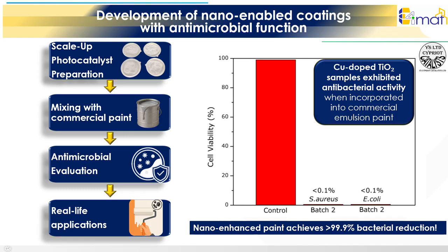The results show a dramatic difference compared to the control paint. While the untreated coating allows full bacterial survival, the nano-enhanced paint achieves more than 99.9% reduction for both S. aureus and E. coli. These results demonstrate that incorporating the copper-doped titanium dioxide particles provides strong antibacterial properties, highlighting the potential of such coatings for real-life applications where improved hygiene and surface protection are needed.